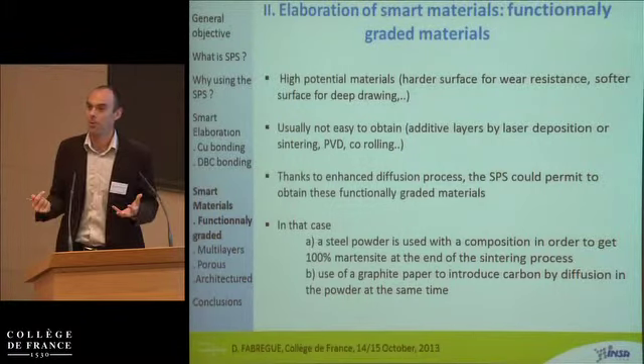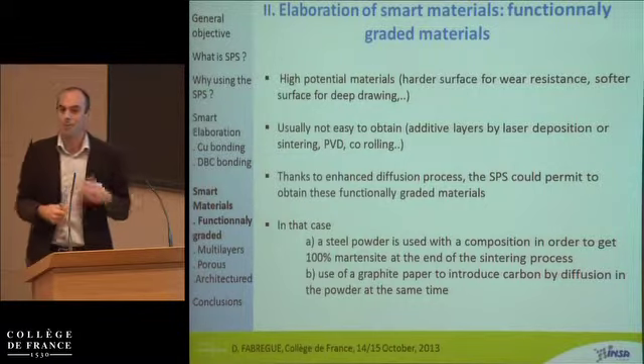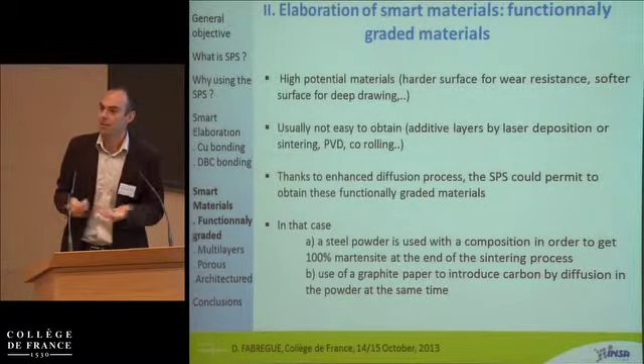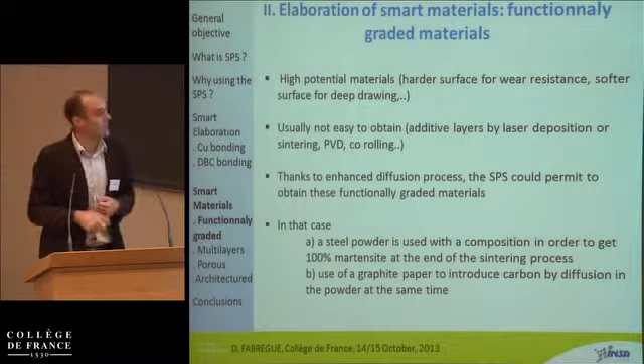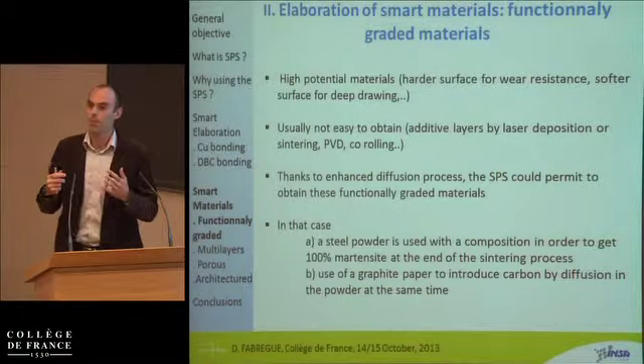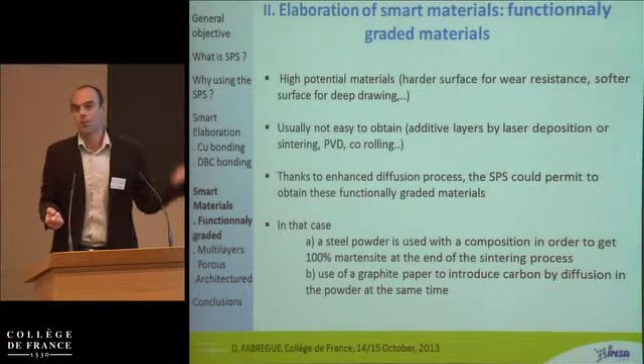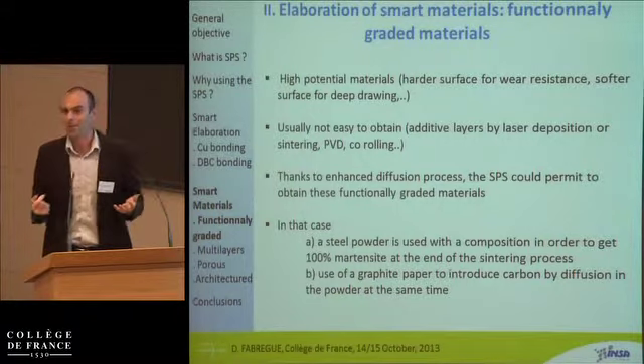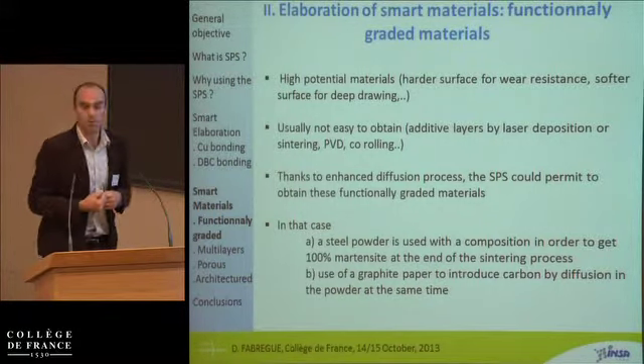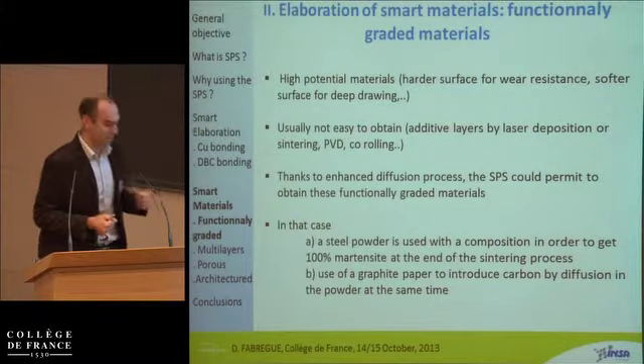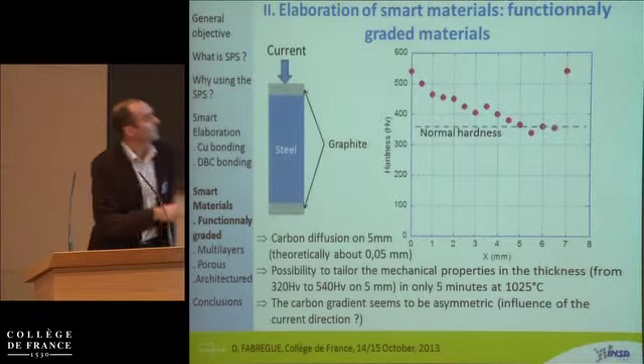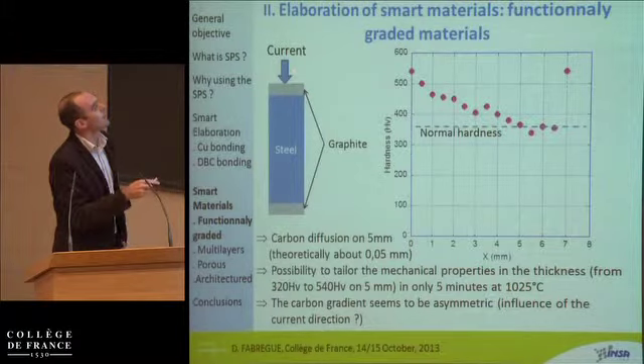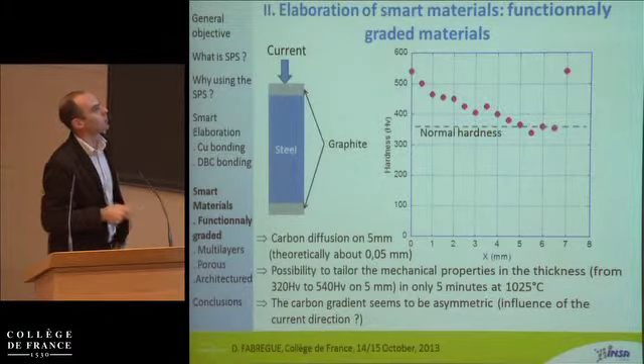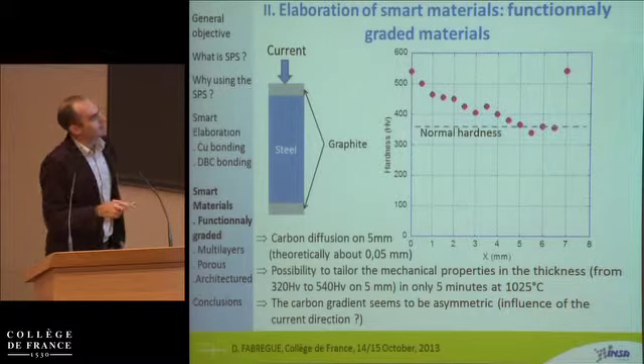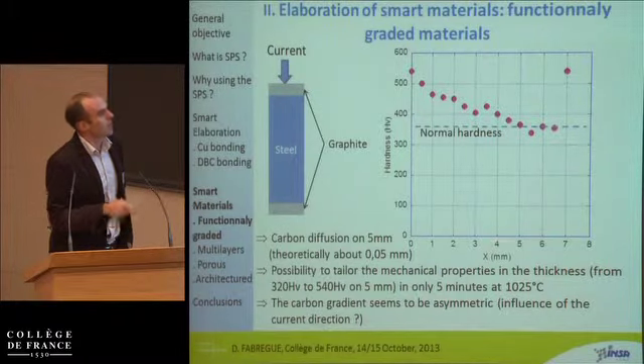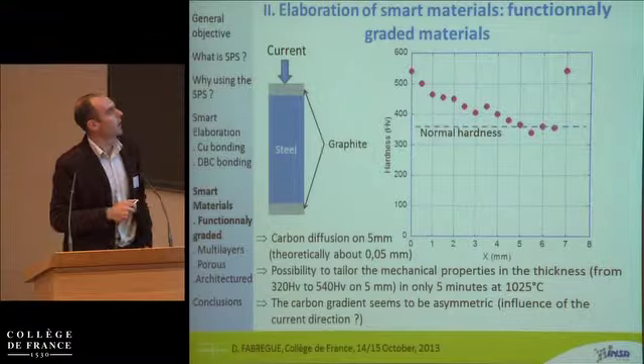So we take a steel powder with a composition that permits 100% martensite at the end of the sintering process. And we use graphite paper as a carbon source to get a carbon diffusion inside the steel powder, and so to have a gradient of carbon inside. So this is basically what happened. This is the steel, we put graphite there, we put the current going through, and this is what you have: the hardness as a function of x. X is the height of your samples.